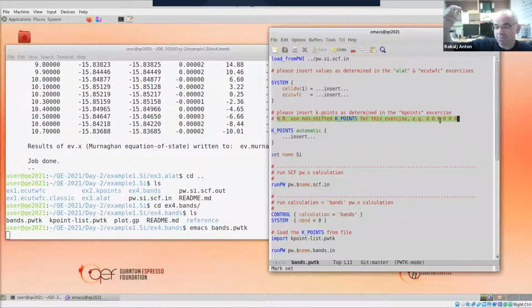And then suppose that you want to get an idea from the density of states plot what the band gap is. If you do not include these critical K points, then you will get a wrong number for the band gap. So for the density of states, it is maybe better to use a non-shifted mesh. If you do this example, and if you first use a shifted K-mesh and then the band structure is plotted, and you compare the Fermi energy, you will notice that the Fermi energy extracted from the shifted K-mesh will be somewhat lower than, let's say, the eigenvalue which should be occupied at the gamma point. So you will figure this out by yourself if you do the example.